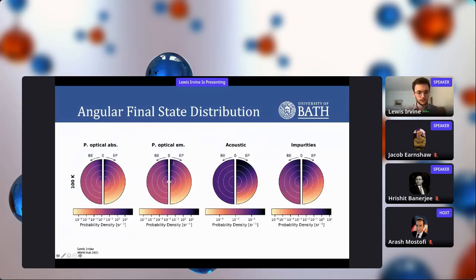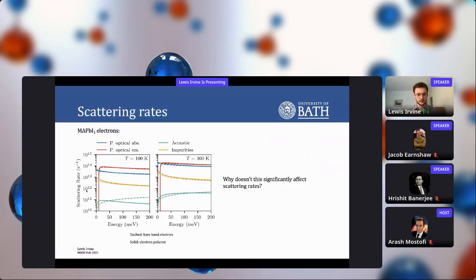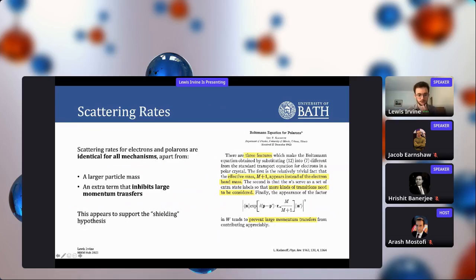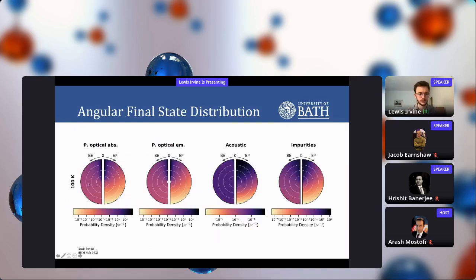So this is what it looks like at 100 Kelvin. For polar optical scattering, both absorption and emission, and also impurities, for band electrons and electron polarons, the final state distributions are still quite highly anisotropic. But adding the electron polaron terms exacerbates that anisotropy. But when you start looking at the magnitudes of probability density, already for band electrons, polar optical phonon scattering is highly forward scattering. It highly favors small scattering angles. So our idea is that although you have this extra term that inhibits large momentum transfers, you're actually inhibiting very few scattering events in the first place.